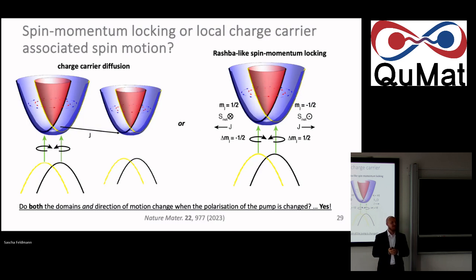Okay. But then there's a second idea, and that would be that because of all this disorder I spoke about, and because of all the symmetry breaking we expect locally, the moment you fully break inversion symmetry in the crystal structure and have these heavy elements and strong spin-orbit coupling, you could also invoke an idea of spin momentum locking in such a Rashba-split system. Now that would mean that if I created a spin-up population, it would flow to this left side, for example, whereas the spin-down population would flow to the right. Then it's locked to momentum.